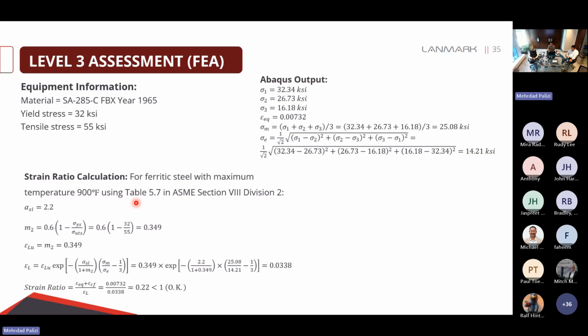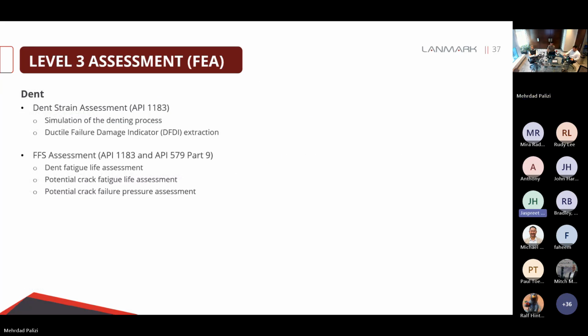So after those calculations, we're going to get some material properties. We go into table 5.7 in ASME boiler pressure vessel code, section 8, division 2. We are getting the material constants. This is the limiting strain, but this is just for the case of uniaxial stress case. So if we are putting it into this relation, we're kind of generalizing it for the multi-axial stress state that we are against. So we get the limiting strain, and then we're going to have equivalent plastic strain divided by limiting strain. If the value was less than 1, that means that point in the structure is okay against local failure. Any questions so far?